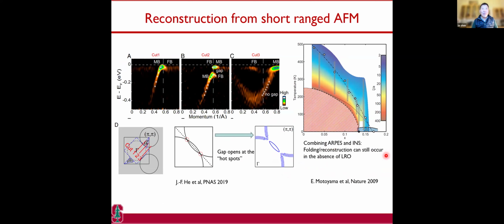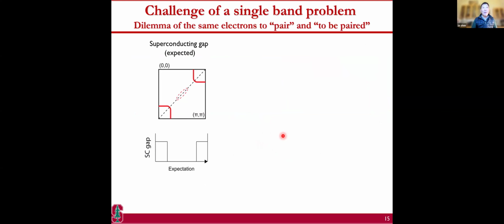Now, more recently, we started to look at this problem again, and in this system we begin to see the other side of the Fermi surface, and you can see the folded band of the pin. So that's sort of a complete Fermi surface, and you can also see the small pocket when it's doped enough, and you can benchmark the volume of this small Fermi surface against the quantum oscillation. They agree quantitatively. So in that sense, we have a pretty good idea of what the Fermi surface looks like in those systems. Okay, now let's come to the interesting problem.